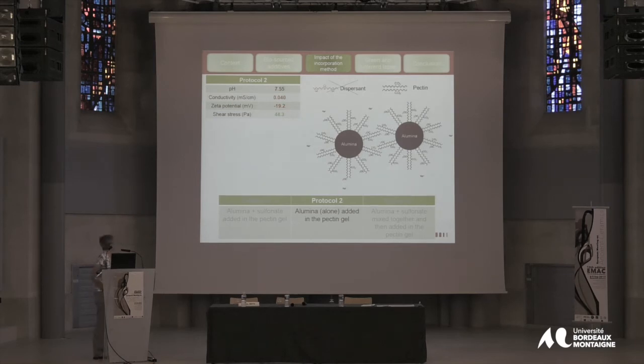Second protocol, without any dispersion, only the pectin. Shear stress is okay, but the potential is not good at all, so we have sedimentation of the suspension. This shows that we need to put the dispersion in the solution to obtain a good rheology.